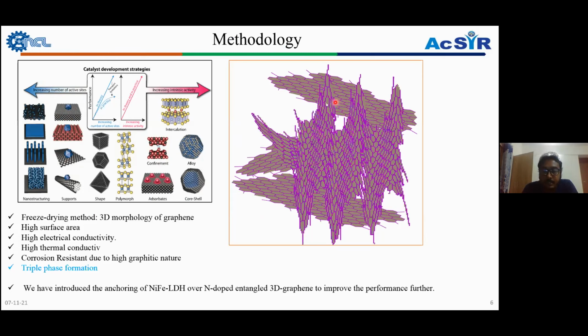So their three-dimensional structure, their individual sheets are connected through a particular angle, which we call a nitrogen doped entangled graphene, because their individual sheets are connected in an entangled form at a particular angle, and there is a porosity. That porosity could help, because in oxygen evolution reactions, the oxygen as a gaseous product is formed from hydroxyl ion. So that hydroxyl ion mass transportation, as well as the oxygen formed, should be removed from the active center.